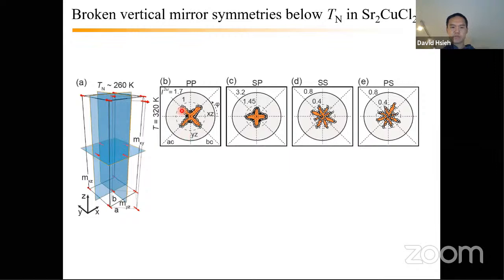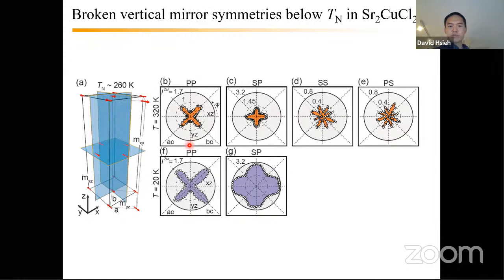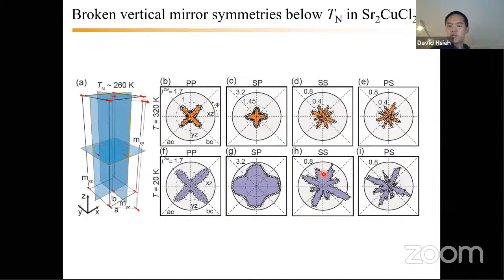Now, as I mentioned, as you cool down below T_N, you preserve the MYZ, MXZ, and MXY mirrors, but you break the mirrors along the AC and BC planes that were there in the crystallographic structure. So you should break AC, BC, but preserve XZ, YZ. In the PP and SP channels, we see a change in intensity, but not really in the symmetries. But strangely, we do see symmetry breaking in the SS and PS channels, but it breaks in a way that violates what one might expect from the Néel order.